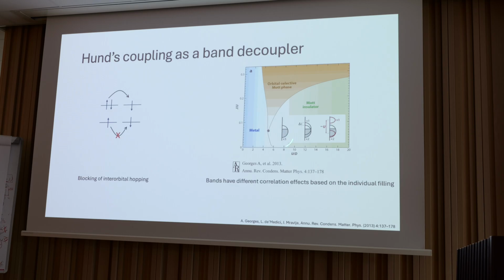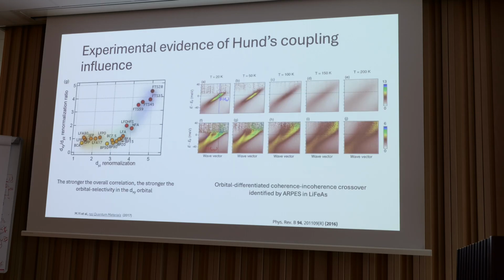So I think this figure here shows these three degenerate bands that get lifted by crystal field, and then the narrower of them is pushed closer to half filling and closer to this orbital selective Mott phase. And then when you keep on increasing U, you can end up in a true Mott insulator state. But there's this concept of the orbital selective Mott phase.